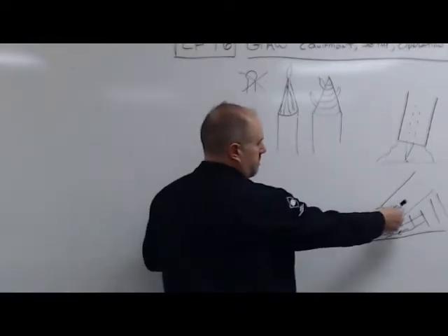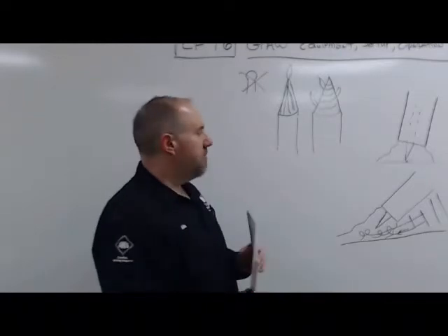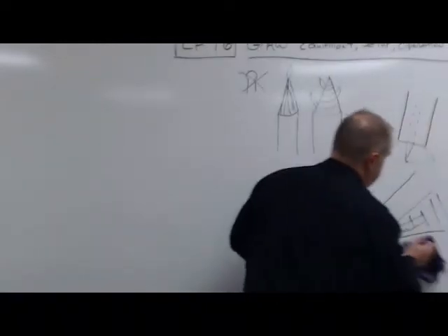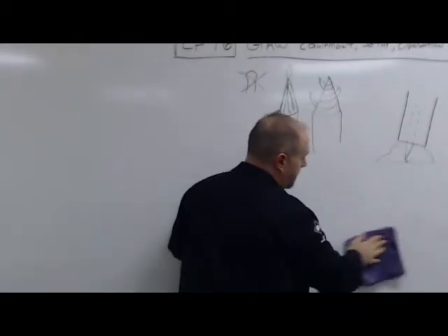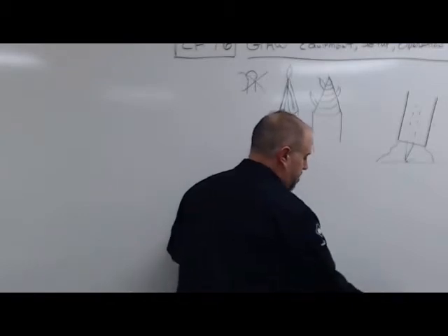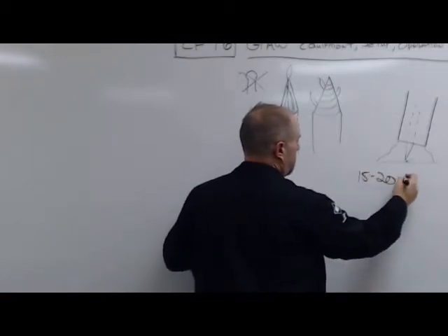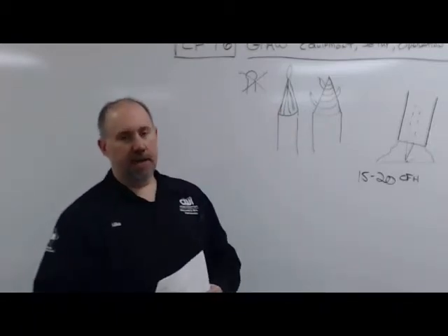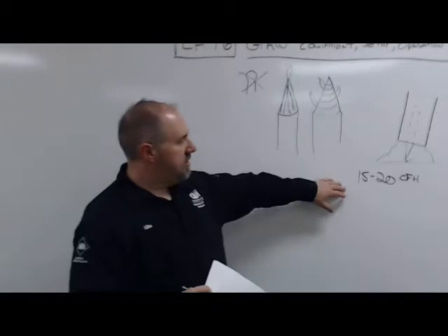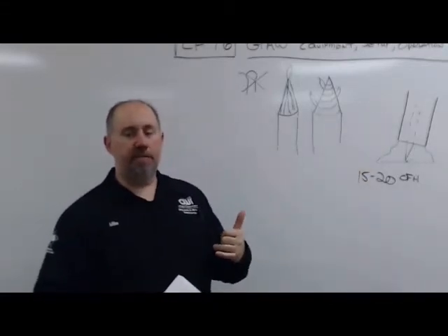So, we want to steepen this back up about like this, and that'll solve 90% of our problems. So, as far as flow rate goes, if you're just running our standard number 7 gas cup, 15 to 20 CFH, that's cubic feet per hour, is what you want. That's a really good starter setting. This will change as we go up in cup size. The bigger cup we have, the more gas we're going to need to get the same amount of coverage.